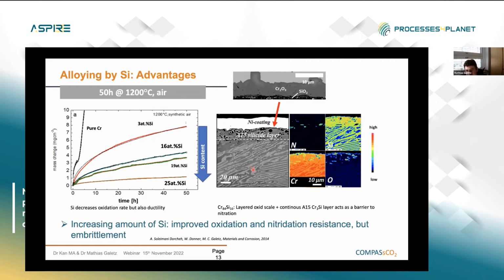As you can see here on the right side, especially the nitridation, this is the nitrogen N signal, is very, very low, and this is usually the biggest problem for chromium-based systems at high temperature. This is the reason why it was abandoned in the 40s, 50s of the last century. All the chromium research basically stopped back then for high temperatures because of this issue. And now with silicon, you can all of a sudden suppress this. So that's why research took off again around 2010. And now a lot is going on with chromium systems again, since you have methods to suppress this nitridation.